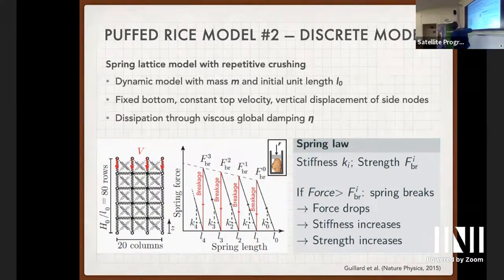There are many springs in each direction. So there are lumped masses here. It's really like the discrete element method that we've heard a lot about, but the contact between the nodes here is characterized by what we imagine would be the typical behavior of, let's say, one grain or a typical collection of grains. So if this is the length of the spring, what we are saying in this very simple starting point model is that we have an elastic response initially, a linear elastic response. The spring is shortened until we reach a critical breakage force. Then we lose the force, the pieces flow, it shatters.